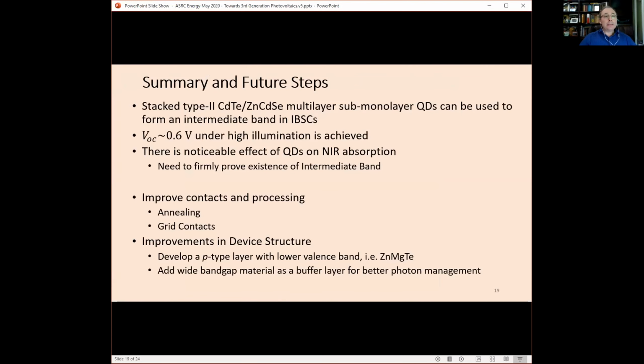So let me summarize that we believe that our stacked type 2 cadmium telluride, zinc cadmium selenide multilayer submonolayer quantum dots can be used to form intermediate band solar cells. We get 0.6 volts open circuit voltage under high illumination. And we have noticeable increase of quantum dot effects under near-infrared illumination.